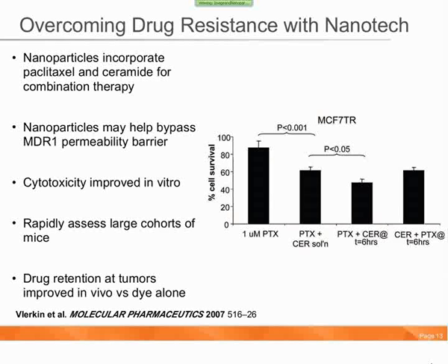One is what's called enhanced permeability and retention, which improves the ability of nanoparticles to be delivered to cells. Fighting against this effect is the significant increase in interstitial pressure that's pushing out on these large nanoparticles. So it's always a balance, and it's important to check to see which is winning in your particular phenotype.